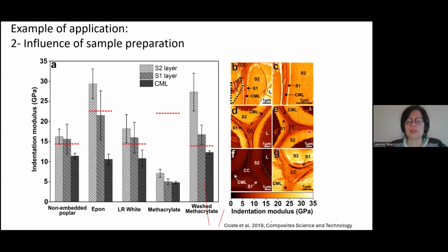So then we did a lot of work on plant cell wall characterization, and for that, how to best prepare the sample so that we wouldn't be measuring just the resin, for instance. A lot of the protocols in the literature use EPON or LR White, different resins to embed the tissues to do microtoming, and that's fine for optical measurements. But when we did mechanical measurement with the AFM and infrared spectroscopy with the AFM, we found that the resin is diffusing into different parts of the cell wall. And also that it's very hard to remove it even after different washes.